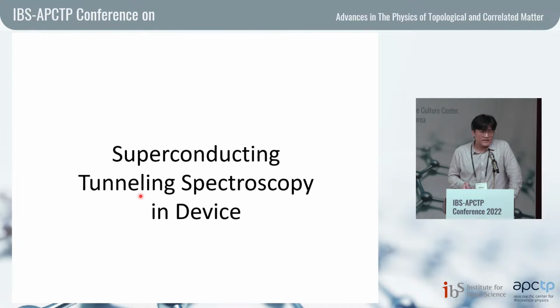But the downside is that if we decrease the frequency of the light, the gap between the original state and the Floquet state will also reduce, because that gap energy is determined by hf. So we need a 3,000 times better energy resolution spectroscopy method to see that. So that's why we worked on making a superconducting tunneling spectroscopy technique at the device level.